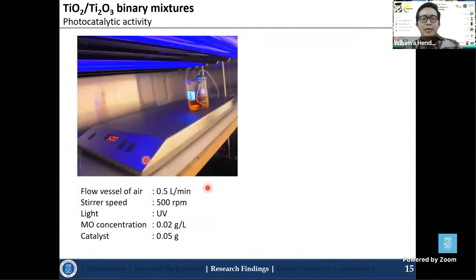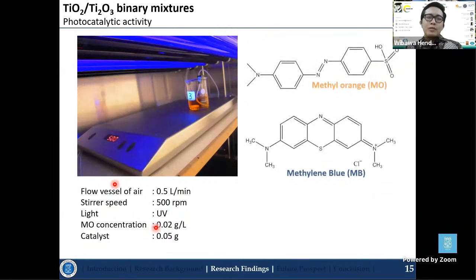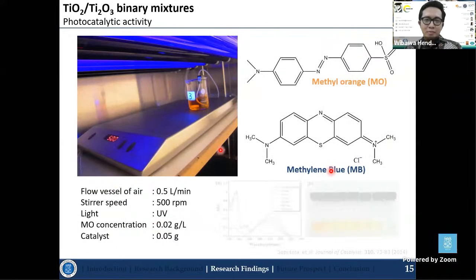So the photocatalytic activity assessments is actually conducted in the lab scale using the home-built reactors. It's very simple, just using a beaker glass. There's a magnetic stirrer in here and also the UV lights, with the catalyst loading of 50 milligrams, and the concentrations of the dye is 20 milligram per liter, or 20 ppm. So I use methyl orange and methylene blue as the model compounds.